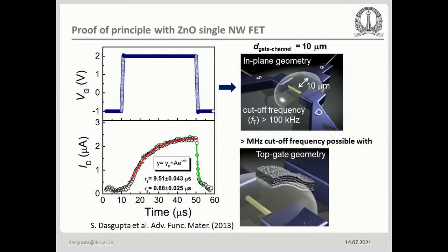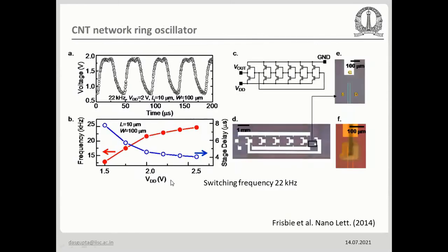This is a nanowire transistor, single nanowire transistor, where we have shown that in fact you can see the tau 1 and tau 2 value, the relaxation time of the order of microseconds. Again, from the Frisbie group, they have shown a CNT carbon nanotube based circuit, which is a benchmark circuit. It is called ring oscillator, where the switching frequency was 22 kilohertz. So up to that level they have shown, and that is the present world record. But there are some other technologies where we will be able to show that even hundreds of kilohertz might be